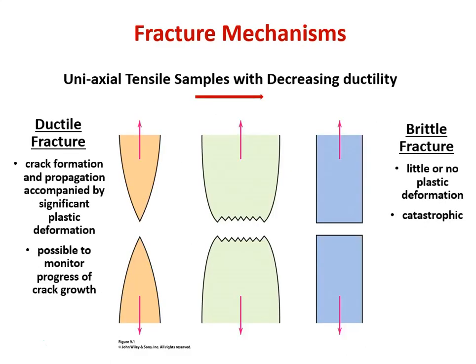Okay, fracture mechanisms. Things can fail either in a ductile manner or a brittle manner, and they have very distinctive appearances. If we take a uniaxial tensile sample, like we learned about in our mechanical properties of material section, a round tensile bar, and we pull on it. Over to the left, we have a very ductile material. It will extend, plastically deform, it'll probably neck, and come down to a point and break over a very small cross-sectional area relative to the original cross-section.